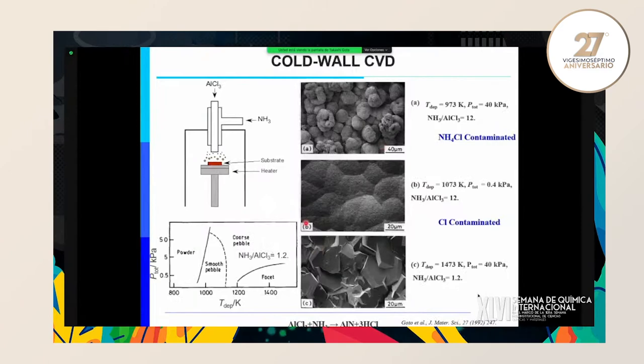But if you use cold wall type CVD, where the substrate is heated by a hot plate or direct current or radio frequency, not heated from the furnace wall, nanoparticle formation is usually less. And then we can find conditions to prepare very good, well-faceted material, aluminum nitride here. Aluminum nitride can be prepared from aluminum chloride and ammonia gas. Aluminum chloride is rather stable compared with many metal organic precursors. Nanoparticle formation is not so significant, but nanoparticles still form even using this cold wall type CVD.